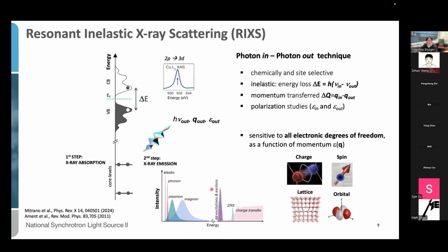In reality, the RIXS spectra are pretty dense. There is a large number of peaks and excitations we can be sensitive to. We can find, for example, excitations corresponding to phonons, plasmons, magnons, and at higher energy, usually in the eV energy scale, we can have orbital dd excitations, and at even higher energy, charge-related excitations. And all of these modes are actually captured in a RIXS spectrum because this technique is sensitive to all the electronic degrees of freedom, as I represented here.